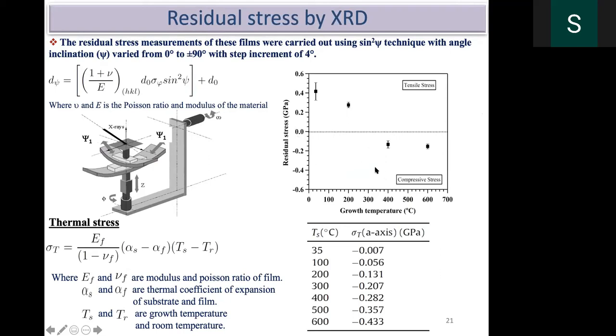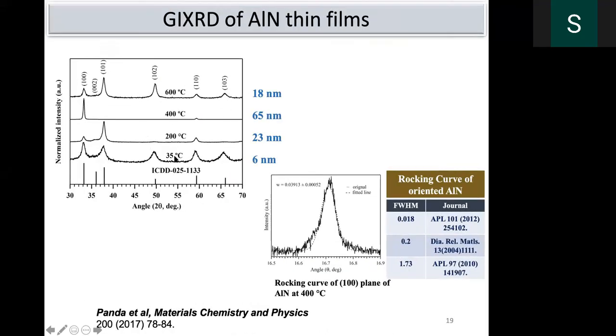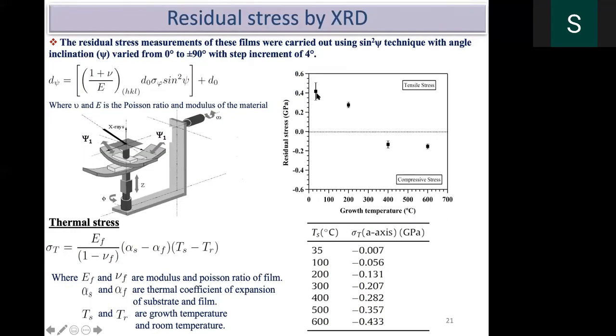We tested the residual stress using the sin square psi technique. You tilt the sample in one particular direction, on the higher 2 theta peaks; in our case, we always take this particular orientation or this one. If you do the sin square psi analysis, the low temperature film exhibited tensile stress. When you increase the substrate temperature, the stress transforms from tensile to compressive. When you have compressive residual stress, the hardness increases.